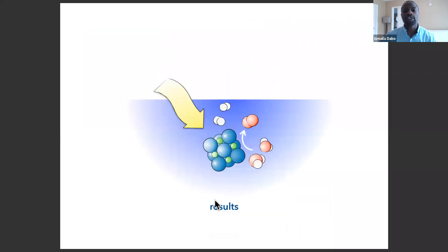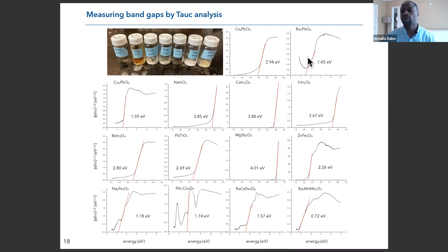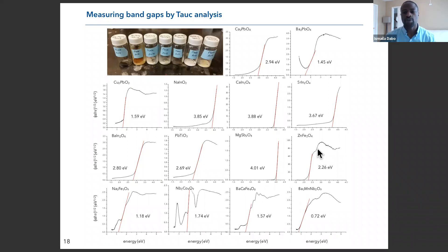For those tests, the first step is to take the synthesized phase-pure powders and look at their optical absorption. We plot the optical absorption times the energy of the incident photon (rescaled) to obtain Tauc plots, from which we extract the band gap by extrapolating the linear portion of the spectra. For most compounds the signature is clear and we can accurately determine the band gap, except for some that potentially contain mid-gap states creating additional peaks in the band gap region.